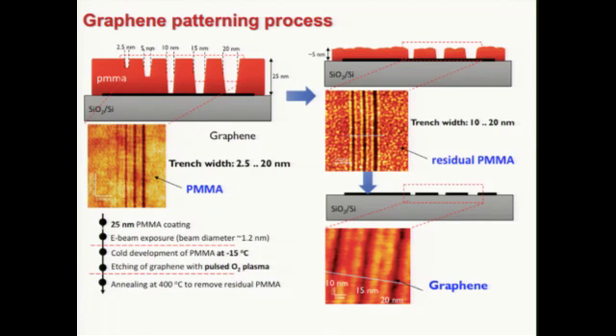About patterning, for high resolution patterning, we use e-beam lithography. We develop the PMMA at very low temperature, minus 15 degrees, to have very sharp features, as you can see here. We could get down to about 10 to 20 nanometer trench width. This is graphene after removing the PMMA residual, so that the patterns are all transferred to graphene. We have 2.5 and 5 nanometer, but as you can see in this schematic, they are not fully developed. So only 10, 15, and 20 nanometer are developed down to graphene.